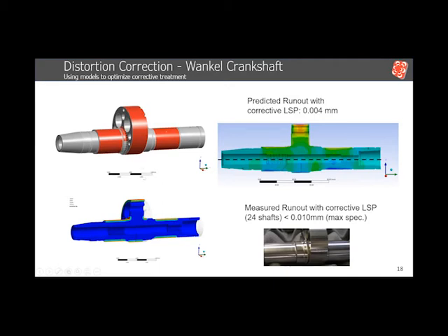And you can see from the model here in the lower left-hand corner, the stress distribution in the part is a result of the additional stresses in the fillet regions between the asymmetric lobe and what occurred. In the process of doing that, we ended up providing shafts that actually met the concentricity requirement for that particular shaft.